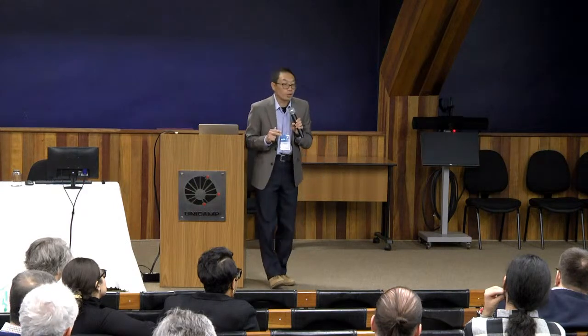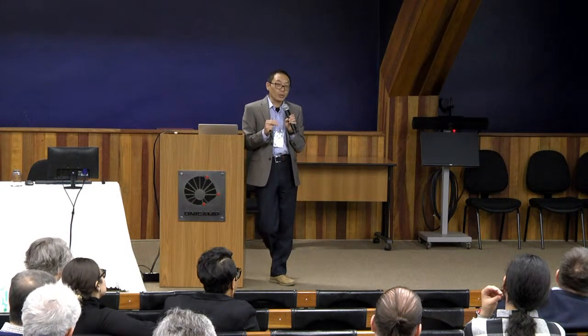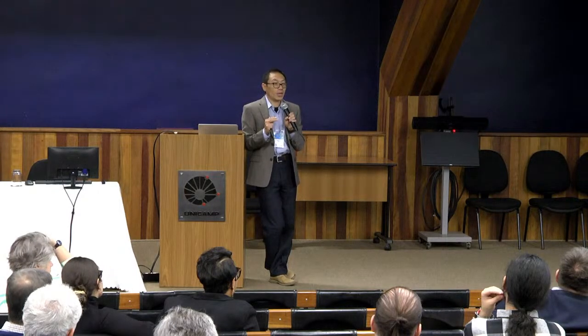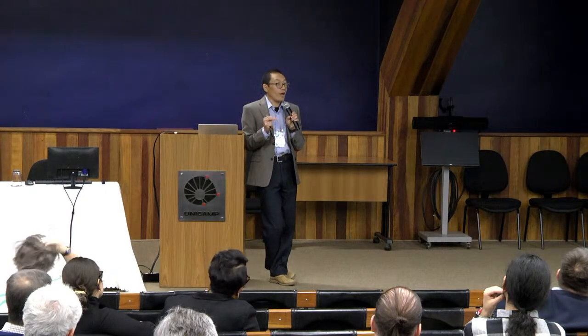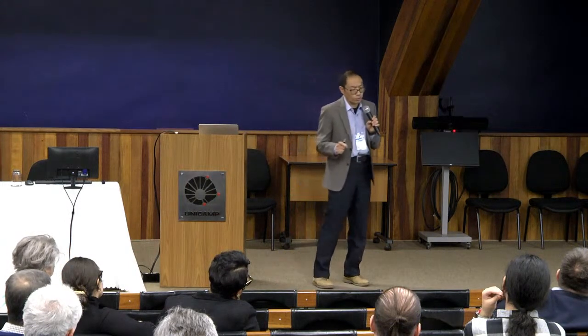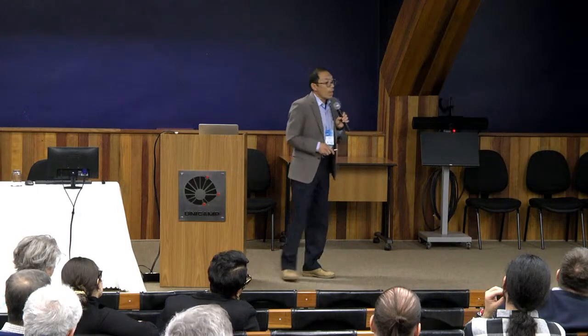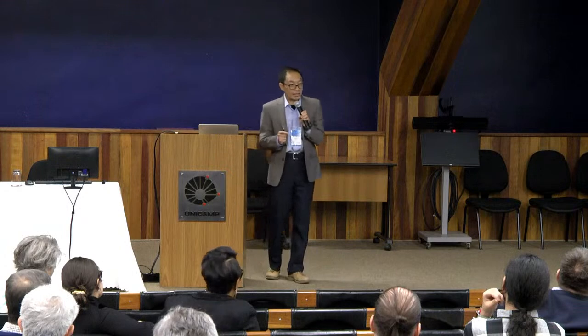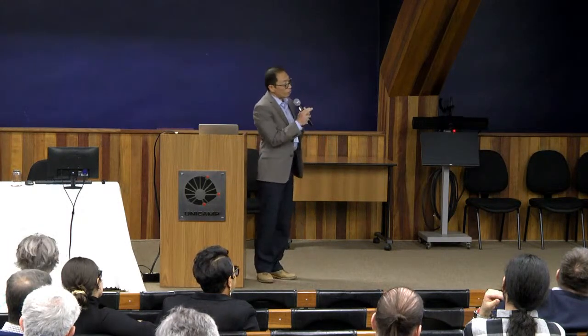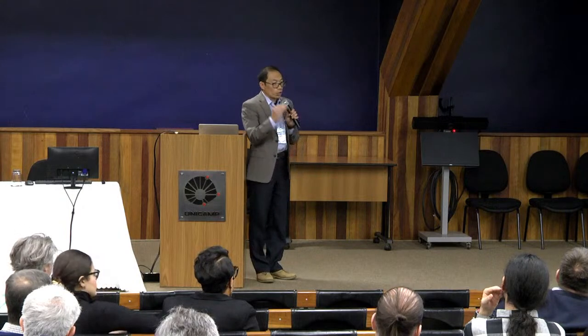In the battery community, it is well known if you charge a transition metal oxide-based cathode to a very high voltage, meaning typically beyond about 4.3 to 4.4 volts, depending on the material, you will see the release of oxygen from the material. And this release of oxygen could be just oxygen gas. That's what I'm showing here.